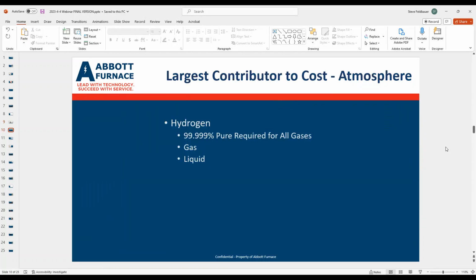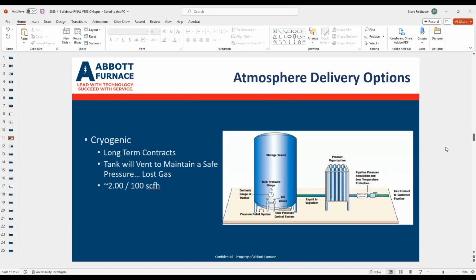So let's talk about that atmosphere, that big chunk. It's going to be hydrogen. You need to have medical grade quality, 99.999% pure, just like any hydrogen-based sintering process. And this can be delivered as gas or as liquid. Most folks are going to be using cryogenic, and that means that it would be delivered as a liquid. You'd have a long-term contract. You'd have a tank. And for this comparison, we use $2 per 100.